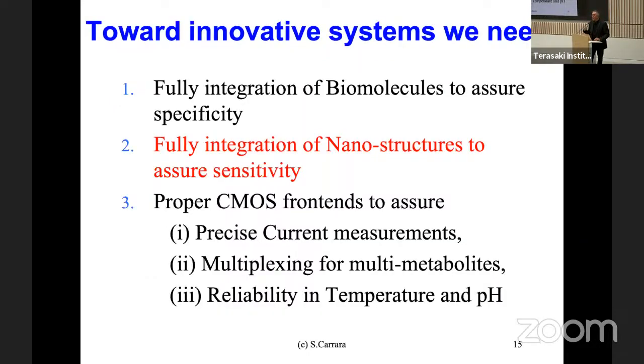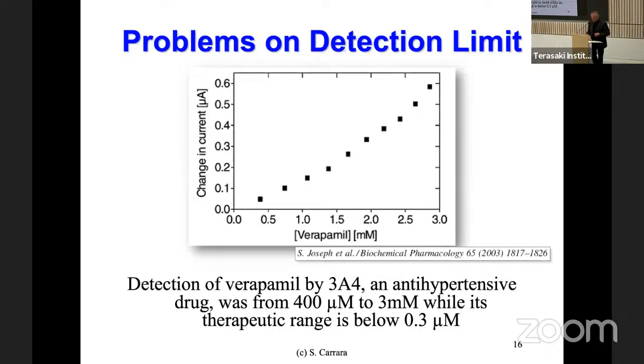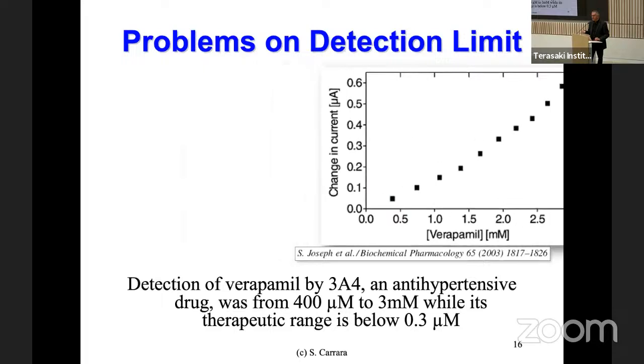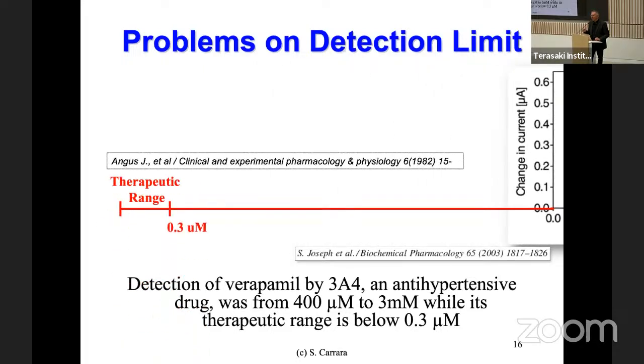Exactly. What about nano? How can the nano help us in drug detection or in ion sensing? Well, this is one example from the literature, the detection of verapamil, a very well-known antihypertensive drug, detected by another isoform, the 3A4 of the cytochrome P450. You see the calibration curve is quite good. We have a linear relationship between concentrations and currents measured. However, we need to see how much is the concentration in the patient's blood. Below 0.3 micromolar. No way to have a real technology based on that sensor, because we are several orders of magnitude blind with respect to what we need to measure in the patient's blood.